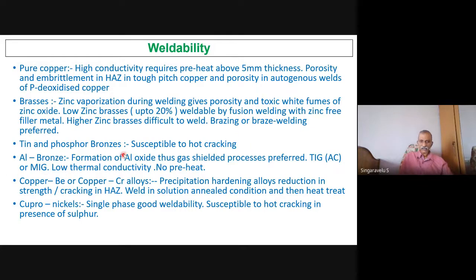Aluminium bronze: aluminium oxide forms, right? To prevent that, go for a gas shielded process like TIG with AC, or MIG. Low thermal conductivity, so no need to preheat for aluminium bronze. Okay, copper beryllium or copper chromium alloys. These are precipitation hardened alloys. As I said, reduction in strength and cracking in the HAZ. Do welding in the solution annealed condition and then do the heat treatment. Cupronickel, single phase alloy, very good weldability, no welding problem, but it is prone to hot cracking when there is a presence of sulfur. Control sulfur, right? Then cupronickel is a very good one from the welding point of view, right?